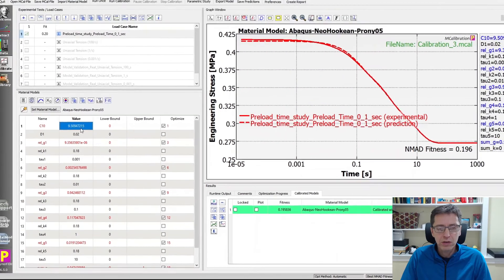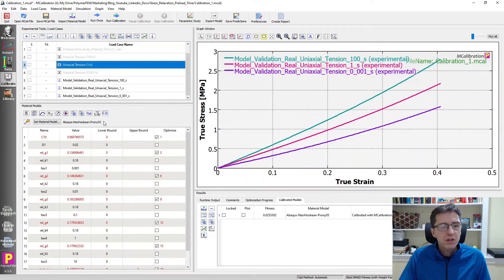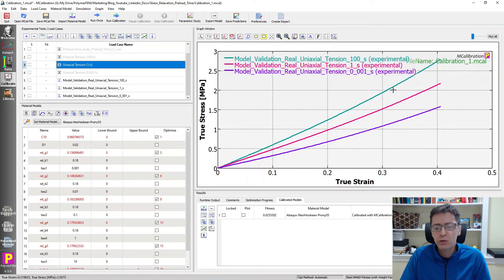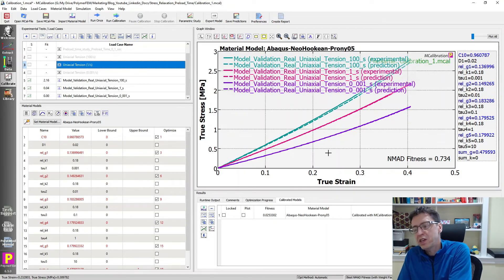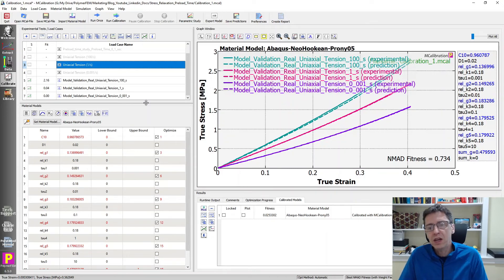Clearly the preload time can have a very large influence on the calibration itself. Let's take a look at these three cases again. This is the first calibration where we assumed the preload time is 0.1 seconds - exactly what was used during generation of the experimental data. I've generated three virtual load cases with tension and I'm going to simulate these. The solid lines are predictions with the original material model. When I calibrated this model to the data generated with it, taking the model, generating data, reading in that prediction and calibrating gives me back very close to where we started. As long as we know the preload time, we're in good shape.